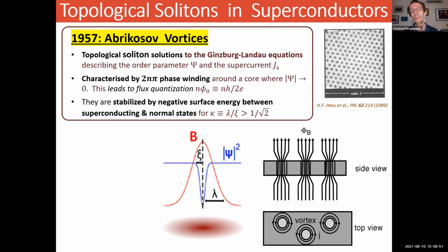Now, the beauty of these Abrikosov vortices and why they are important for today's discussion is that they are characterized by 2nπ phase winding around the core, where psi, the order parameter, and here is a typical vortex core down here, would go to 0. And this leads to flux quantization. They're also stabilized by negative surface energy between superconducting and normal states for as long as the ratio of the penetration depth, lambda, shown here, to the coherence length, xi, is greater than 1/√2.